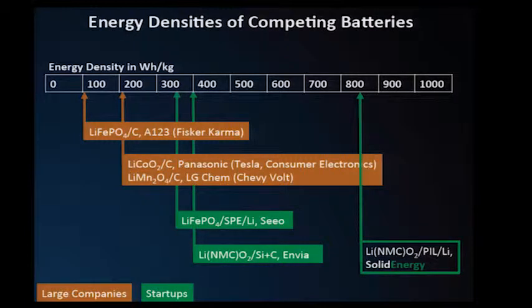But I stress that this is only one of about five critical figures of merit. High temperature bulletproof operation is another one. So you can park your car in a Phoenix parking lot exposed to the sun for a week and you don't come back with a really dead battery, things of that nature. And cyclability, 5,000 would be a minimum, but you'd really want maybe 8,000 to give you 15 years of moderately deep discharge cycles.